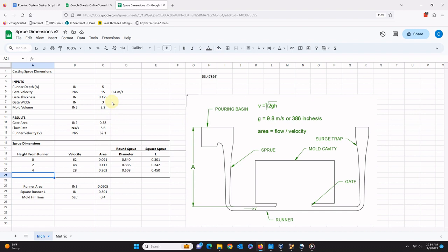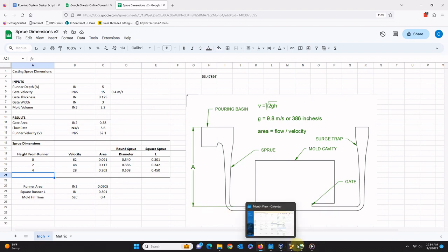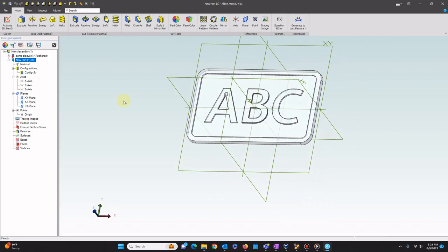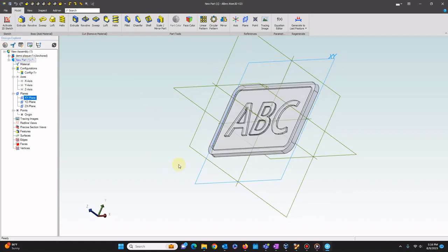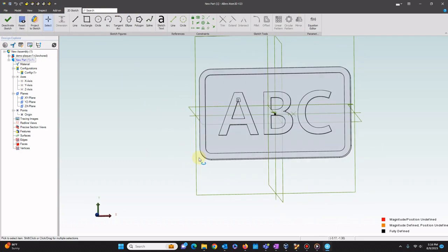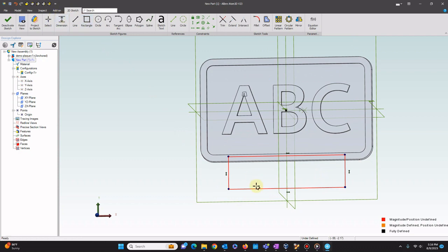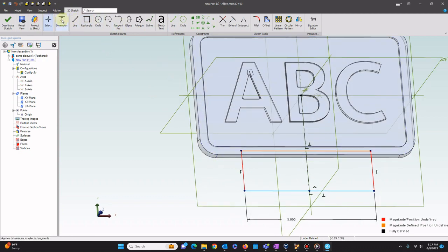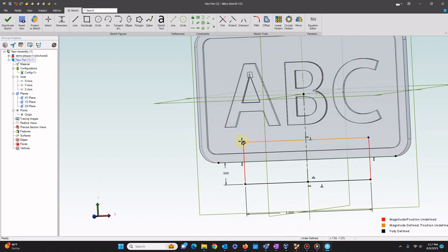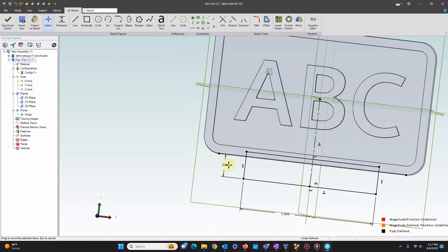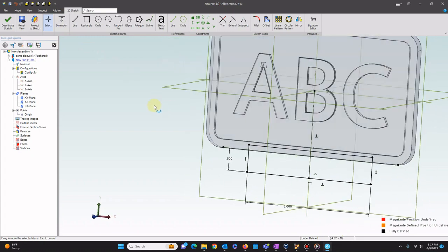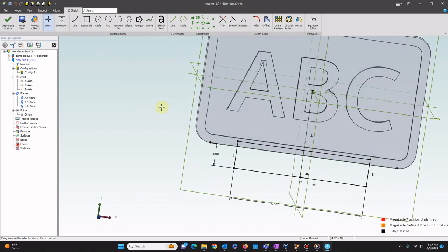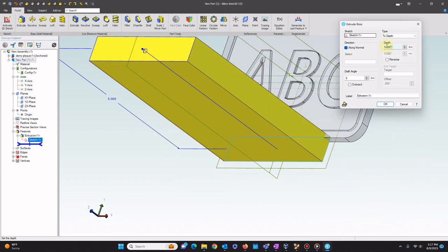With the critical dimensions calculated, we can now begin modeling the running system. In the case of a vertical mold, all the parts can be designed as a single printable part. With a single piece running system, it is best to go backwards from the direction of metal flow, starting with the gate into the mold cavity. Here we follow the dimensions in the spreadsheet. Make sure to add some draft. Five degrees is good. We will make it about half an inch long here to make it easy to mold as much as anything else.